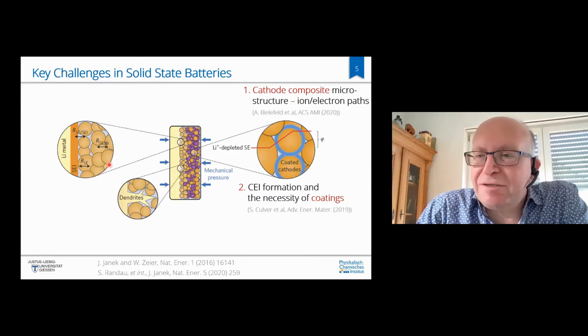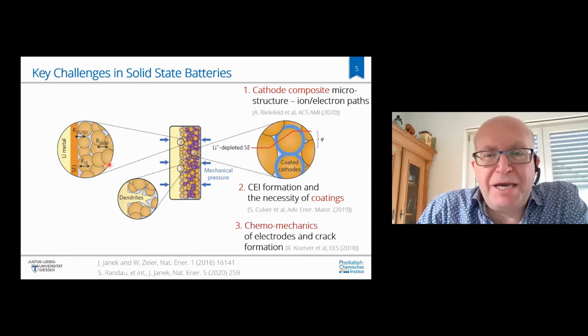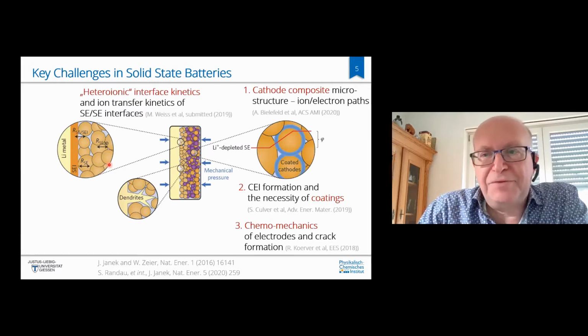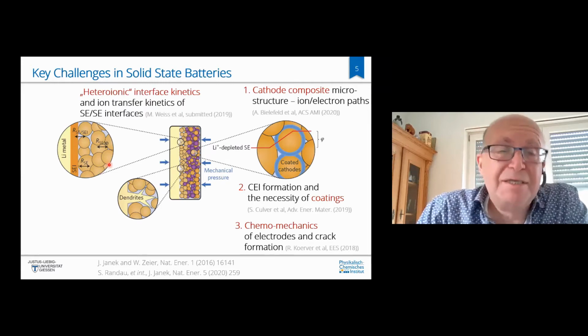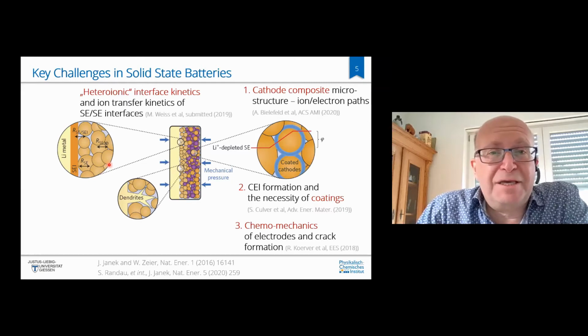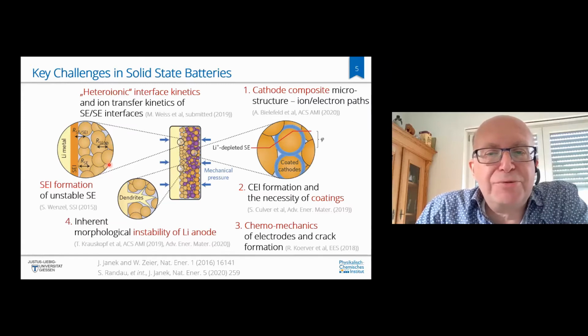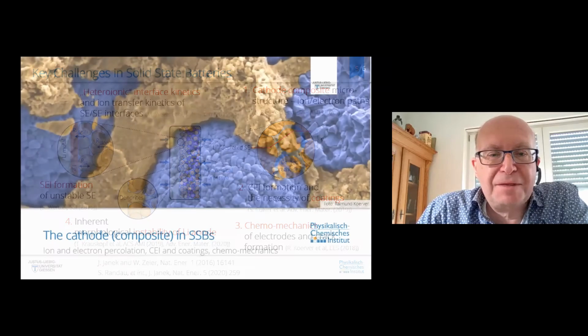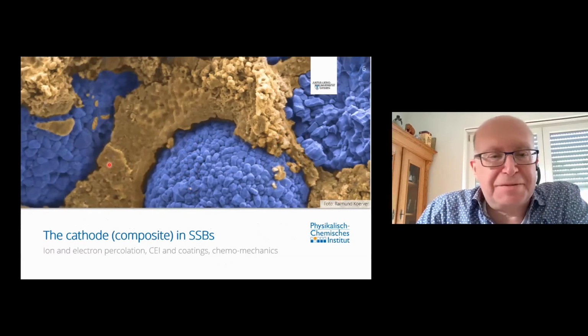We will see that, in fact, the best solid electrolytes are not very stable at the cathodes, and there is a CEI formation, and we have to avoid that. Chemomechanics plays an important role because the best electrolytes are more or less ceramics, so we have to look at chemomechanics. I will not speak about heteroionic interface kinetics and SEI formation at the anode side, but I will then move on to a kind of model type study to understand better whether lithium metal anodes really can operate with solid electrolytes. Okay, so let's start with the cathode side.